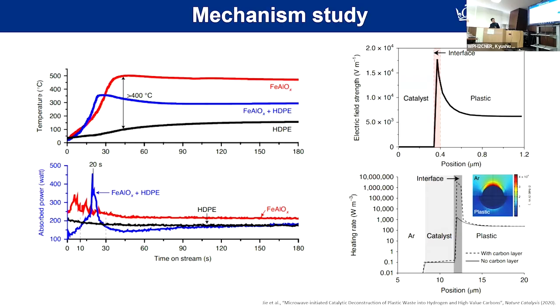And this peak here, the jump in absorption power, actually indicates that the reaction occurs, because once the sample's dielectric properties change, it is reflected in the absorption power. So you see that at 20 seconds is the peak of the microwave absorption, and all of a sudden it decreases to a very low level. And from our characterization by XRD and SEM, TEM, we find the polymers are almost completely decomposed in only about 20-30 seconds. Some simulation was also done on how important the interfacial condition or environment is. Here we only simulate the catalyst and the plastic, and you will see the electric field between these two is several times higher at the interface.